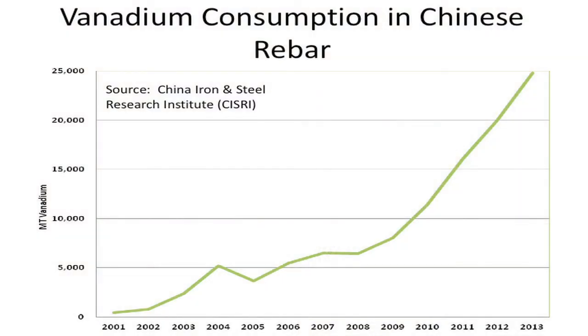And so what you've seen now, as this grade 3 standard's been adopted in China, is a massive explosion in consumption. So we're talking about 25,000 tons of vanadium, which is, somebody smarter than me can do the math, but that's 40% of global consumption in a new application that didn't even exist 10 years ago. And there's plenty of room for this phenomenon to continue. If you look at what's going on right now, the percent of rebar that's being produced in China that's meeting this grade 3 standard is still only about 60% of the total. So this 25,000 tons can easily turn into 40,000 tons over the next couple of years.